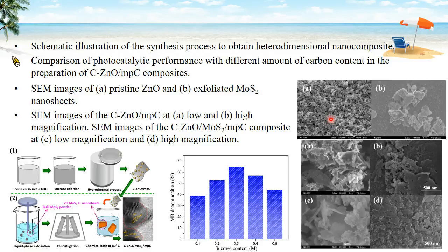Next, we prepare few-layer molybdenum disulfide nanosheets by LPE technique. These dried exfoliated 2D molybdenum disulfide nanosheets show plate-like geometry. They are centered on the binary composite by wet chemical treatment. This gives the ternary composite. We see very thin molybdenum disulfide nanosheets incorporated in the composite. This porous 3D skeleton is beneficial for solution infiltration, reduced carrier diffusion lengths, and abundant active sites.